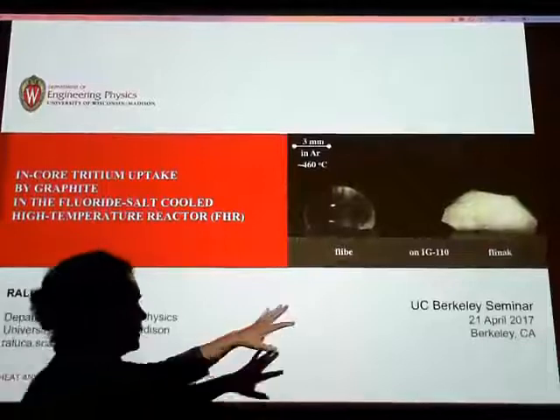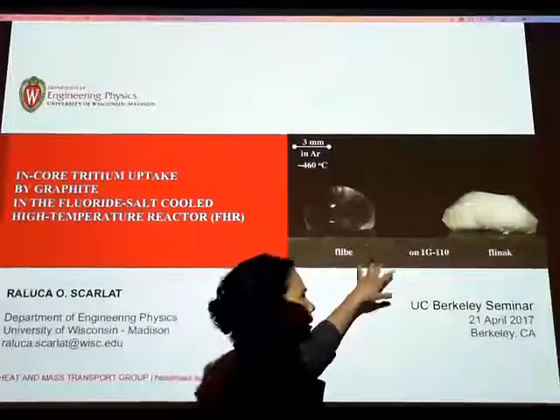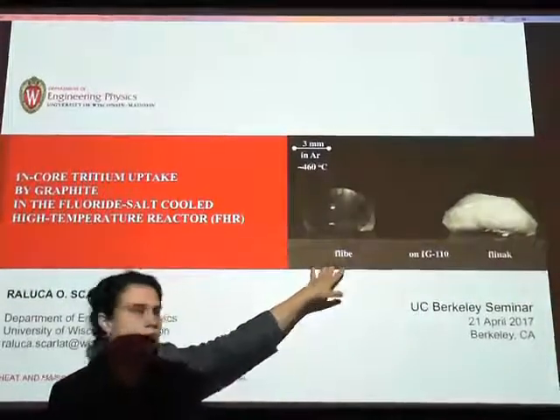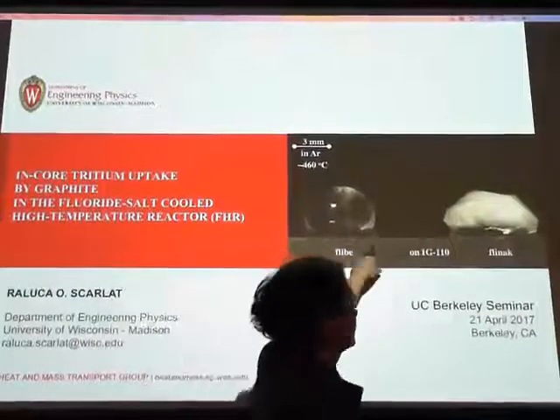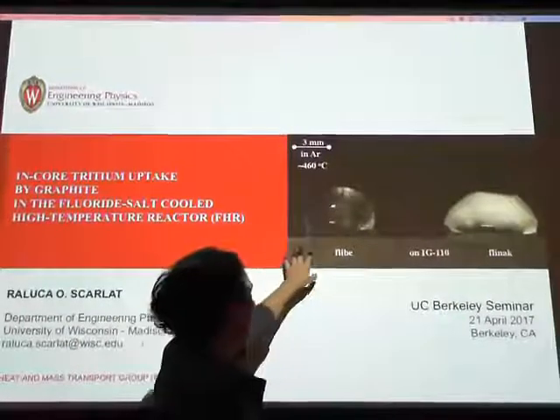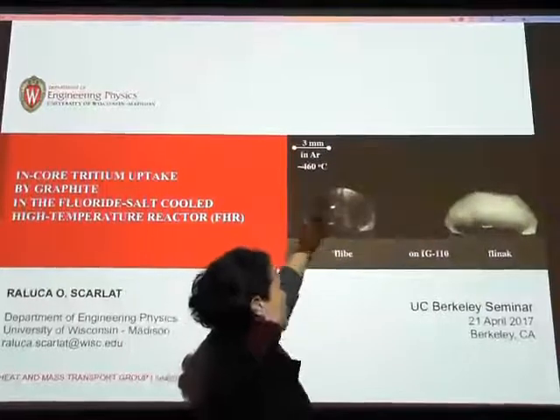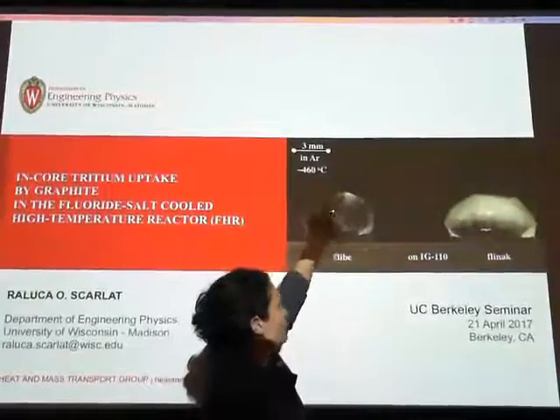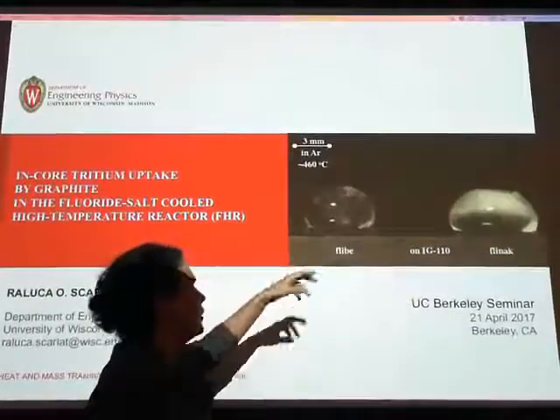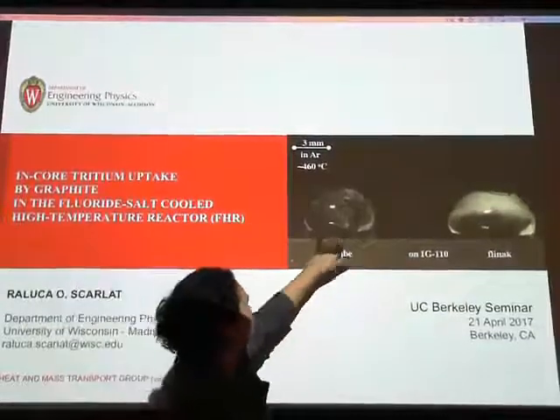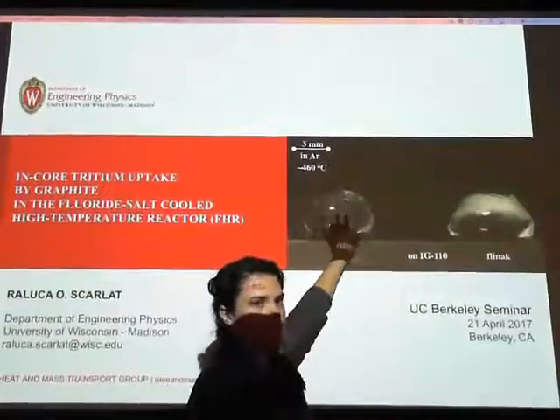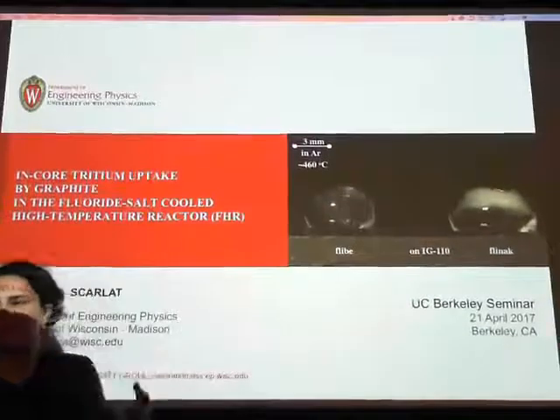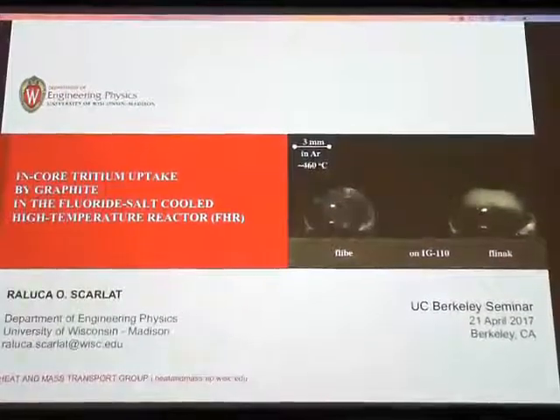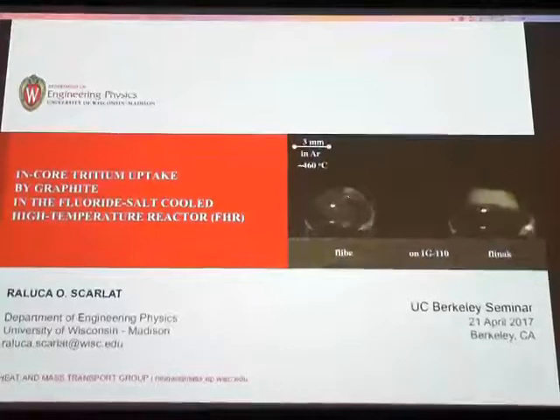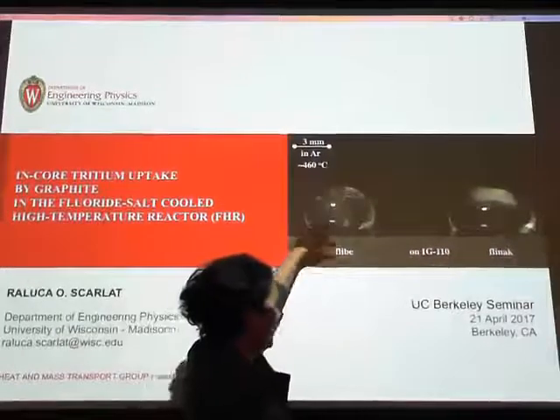And so what you see here are two droplets of salt that are melting on a nuclear graphite surface. This is flibe, and you can see that this salt is recirculating. And what's remarkable about this is that this is a 3 millimeter droplet. The movie is sped up about 8 times, so it's a little faster than real time. And the temperature gradient is probably very small.